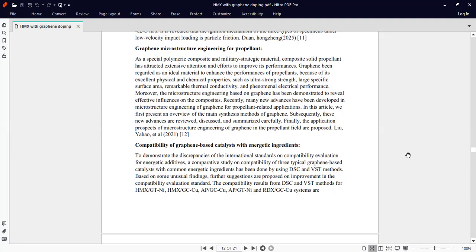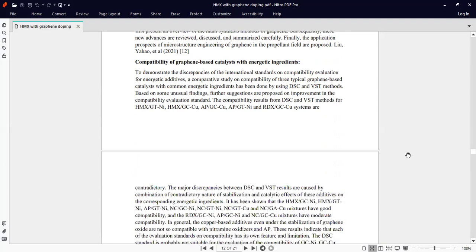Now, the first topic is the compatibility of graphene-based catalysts with the energetic ingredients. To demonstrate the discrepancies of the international standard on compatibility evaluation for energetic additives, a comparative study on compatibility of three typical graphene-based catalysts with common energetic ingredients has been done by using DSC and VST methods. Based on some unusual findings, further suggestions are proposed on improvement in the compatibility evaluation standards.